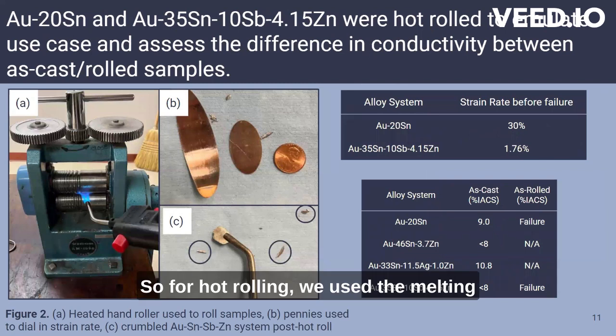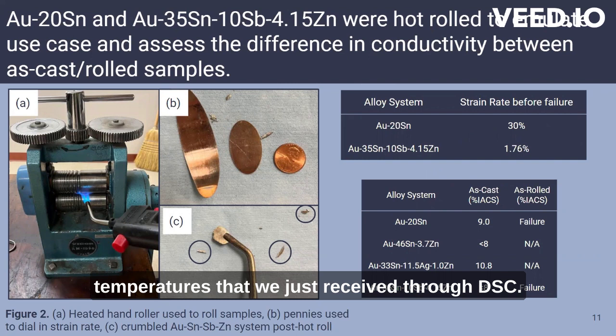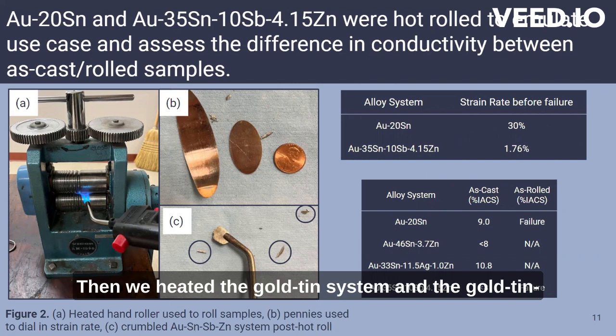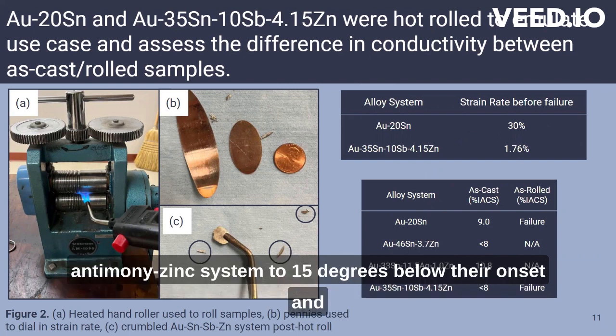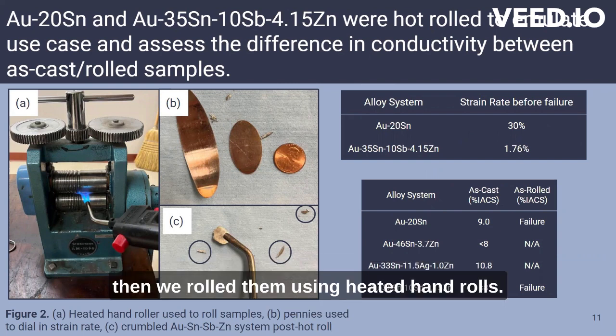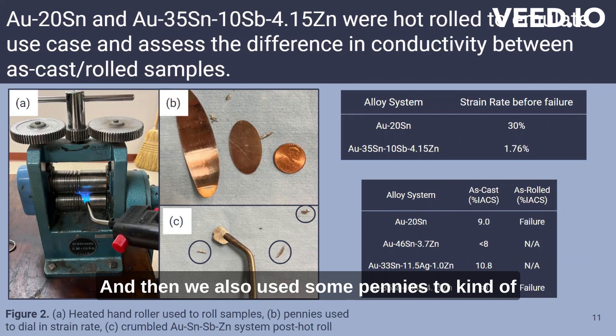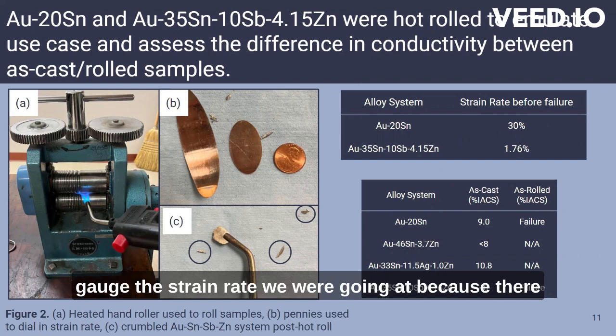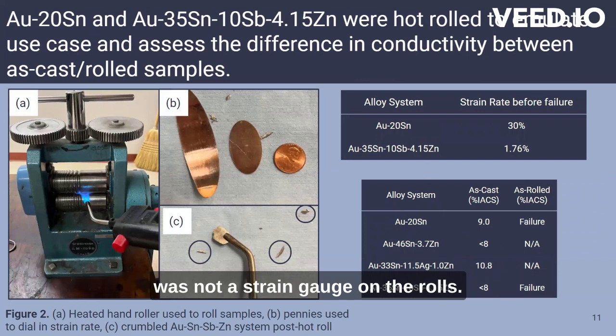So for hot rolling, we used the melting temperatures that we just received through DSC, and we heated the gold tin system and the gold tin antimony zinc system to 15 degrees below their onset. And then we rolled them using heated hand rolls. And then we also used some pennies to kind of gauge the strain rate we were going at, because there was not a strain gauge on the rolls.